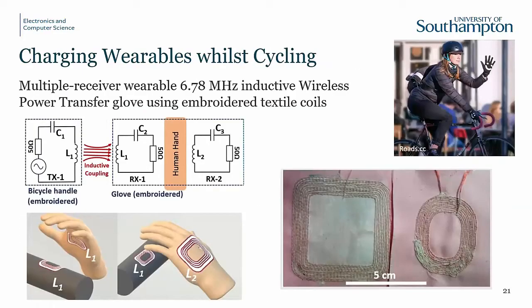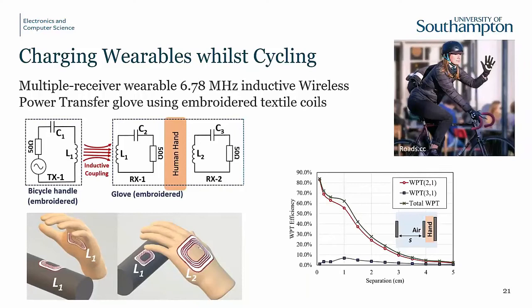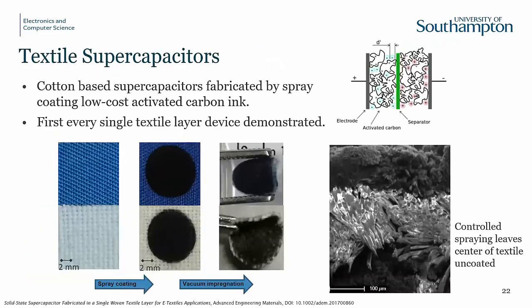The latest thing we're doing is transferring this onto a bike as another use case example, where you have a coil on the palm of your hand on your cycling glove and a coil on the handlebar, and you can recharge your wearables and your e-textile devices as you cycle along. We've looked at various arrangements of where you put the electrodes, on the back or the front of the hand, for example, and we get transfer efficiencies of up to 80-85%. So that's the energy harvesting or energy capturing point of view.